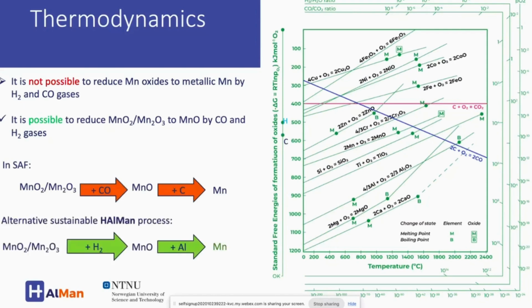But in HAlMan process, what we do is first conversion of manganese oxide to MnO by using hydrogen, and then thermodynamics says that it is possible to reduce this MnO further to manganese metal. So instead of carbon, we use aluminium. This aluminium is not expensive since we target to use aluminium scrap and aluminium containing waste like aluminium dross.